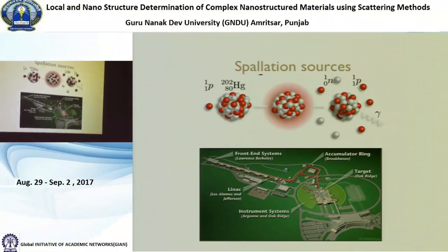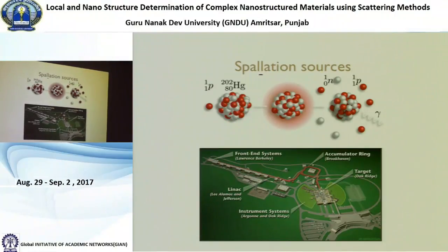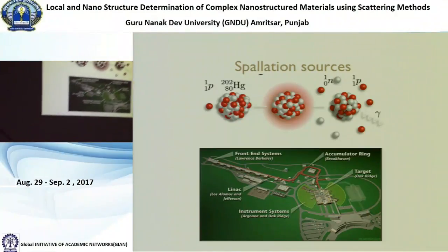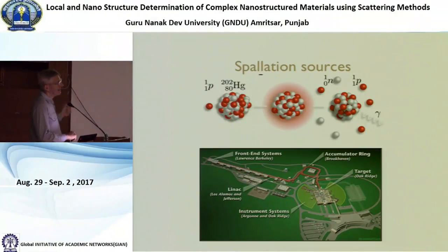You know when the neutron was created: that's when the proton pulse hit the target, and you start a clock. You let the clock run, and the neutron comes into the moderator, goes down the tube, hits your sample, and finally ends up in a detector, and then you stop the clock when the neutron hits the detector.